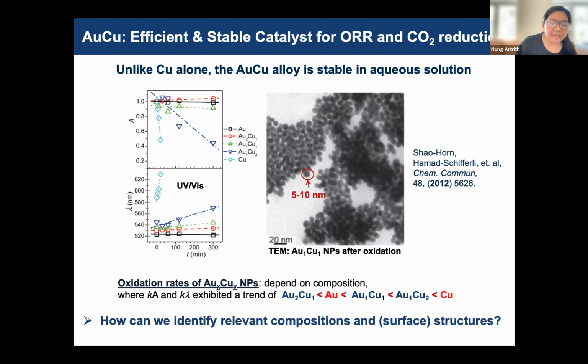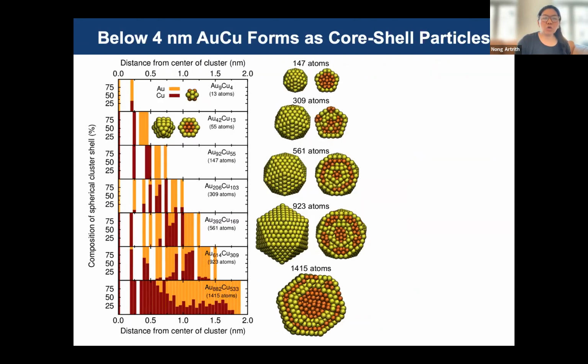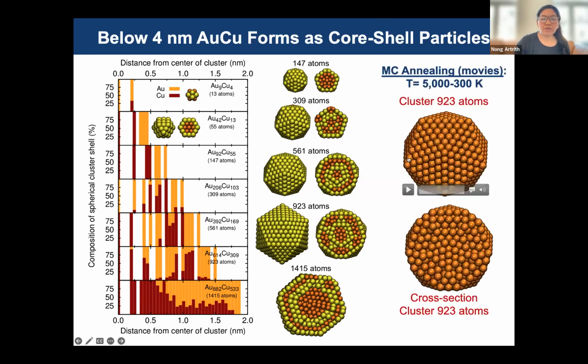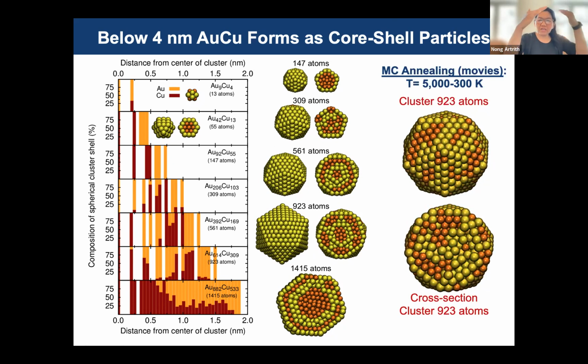So, as a computational materials scientist, how can we help to identify the important compositions and also the surface structures? We develop machine learning models with DFT reference data, and then we construct many different sizes of copper and gold nanoparticles. We apply our NN potentials and use them in Monte Carlo annealing to search for different types of compositions.